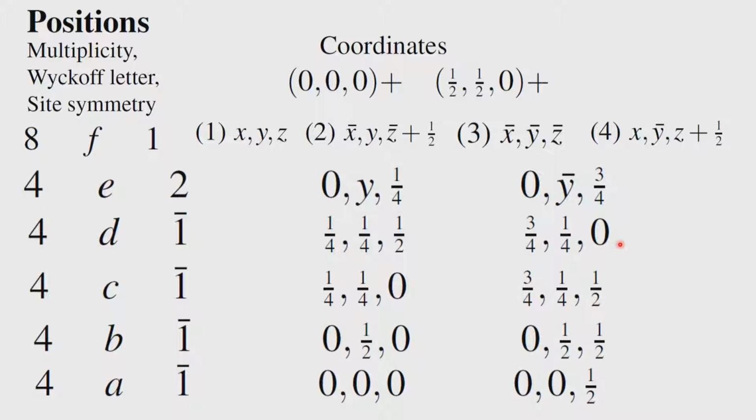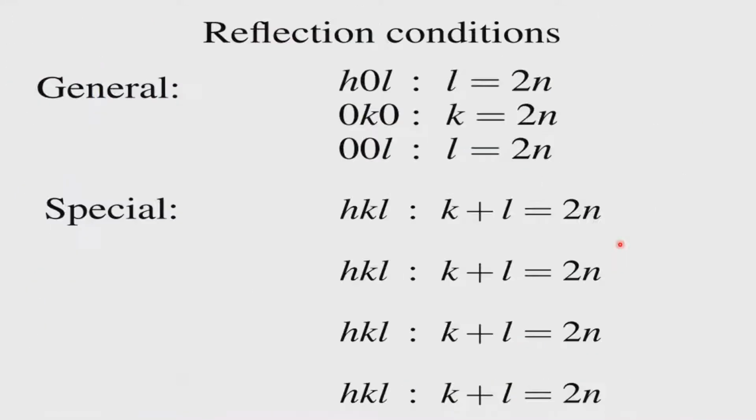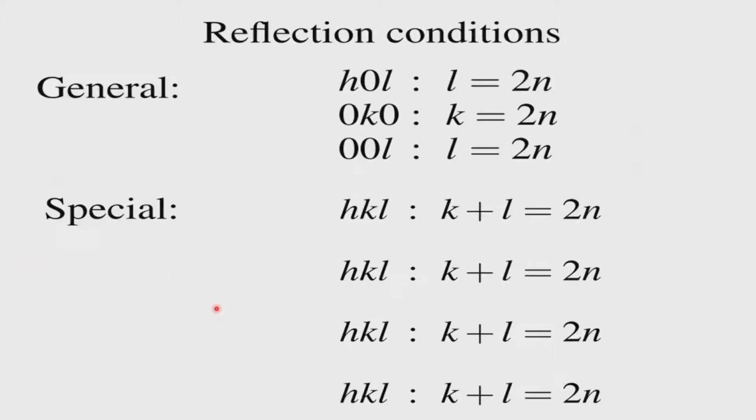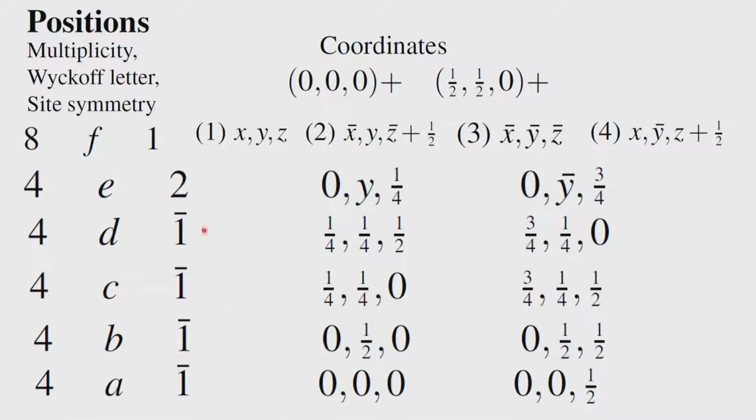And then we have several sets of special positions in this. You notice that all the special positions generate 4 equivalent points, even though there are 2 types of special positions which come up. You see, in so far in the previous examples up to this point where we discussed P21 upon C, the special positions had the same symmetry. In this case it was 1 bar, but if you come to C2 by C, you see that the special positions are of 2 kinds.